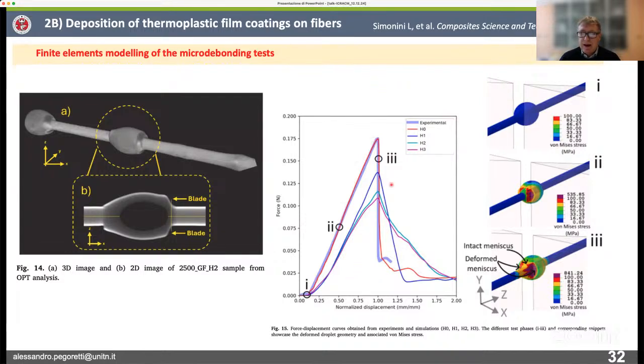And at the same time, we can observe that after the first healing, a drop in the force is observed due to the change in the geometry. So this drop in the force is not necessarily associated to a drop in the adhesion. So we have to take into consideration this effect in order to correct somehow the model and the prevision of the model on the interfacial adhesion.